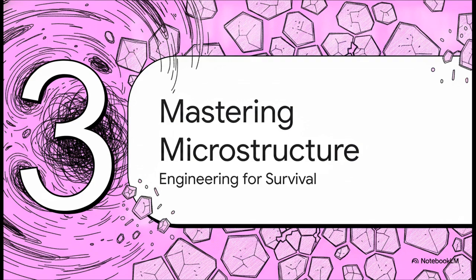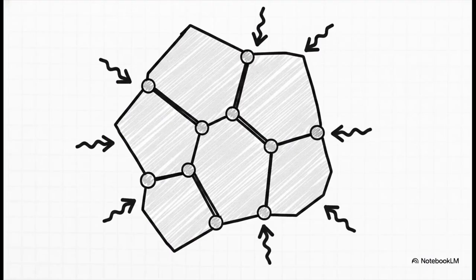Section 3, mastering the microstructure. Now, to survive at Mach 5, we have to look at a fascinating concept called grain boundary segregation engineering. Scientists aren't just mixing powders anymore. They're literally manipulating the physical interfaces between microscopic grains. By adding very specific dopants, they can pin these boundaries, stabilizing the ceramic at a scale of just a few nanometers. Think of it like microscopic superglue that stops the grains from sliding and deforming under immense stress.